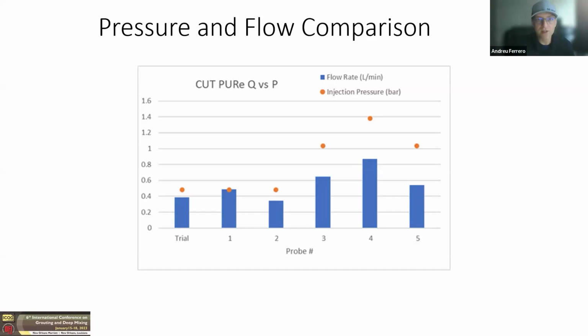This is a pressure and flow comparison for the cut pure polyurethane. So as you can see, the flow rate changes slightly with an increase in pressure. As we increase that injection pressure, we are getting a slight increase in our flow rate. And that makes sense because the material is about 180 centipoise viscosity. So it's not really thick, but it's relatively thick compared to water. So as we increase that injection pressure, we do see an increase in flow rate, but it's not exactly linear. You've got to increase that pressure a little bit higher to just start slightly increasing that flow rate